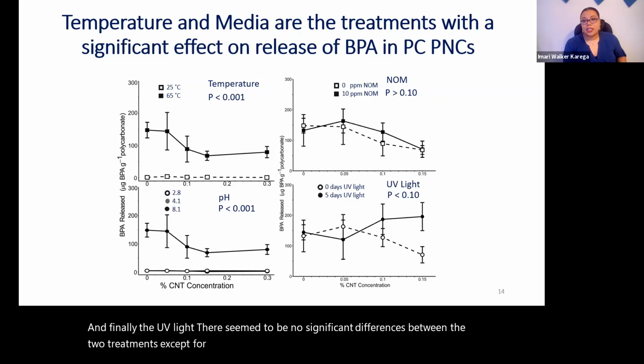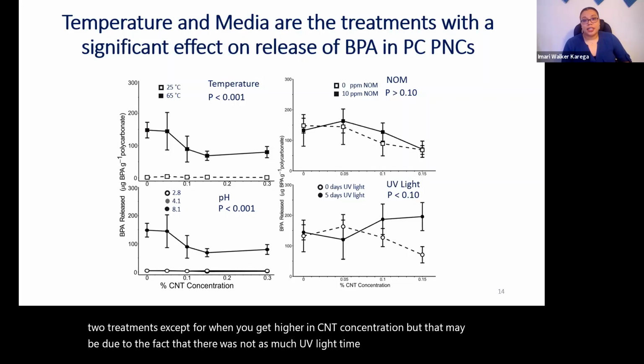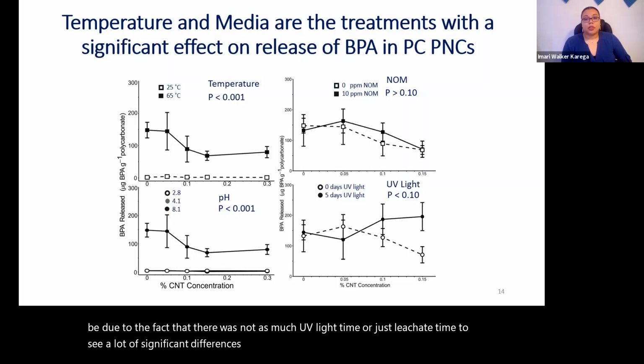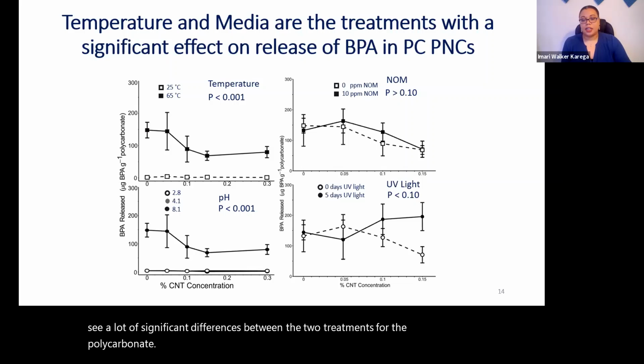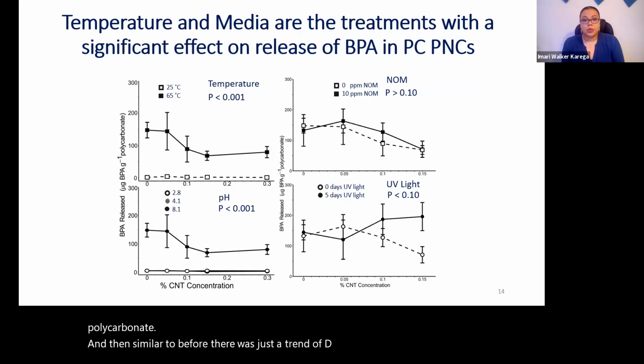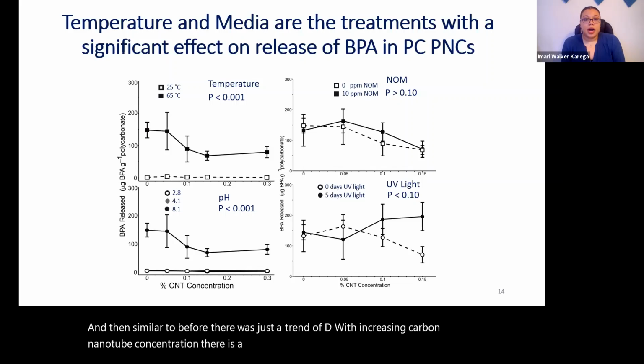get higher in CNT concentration. But that may be due to the fact that there was not as much UV light time or leachate time to see significant differences between the two treatments for the polycarbonate. Similar to before, there was just a trend of increasing carbon nanotube concentration leading to a decrease in the amount of BPA released in these polycarbonates.